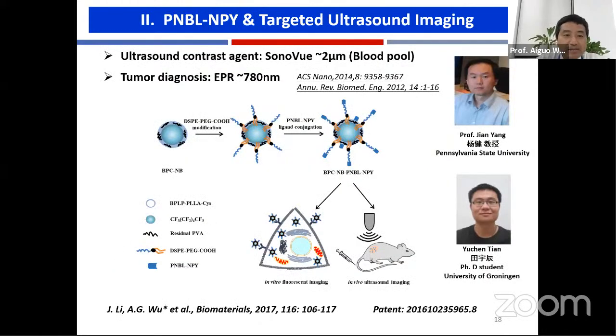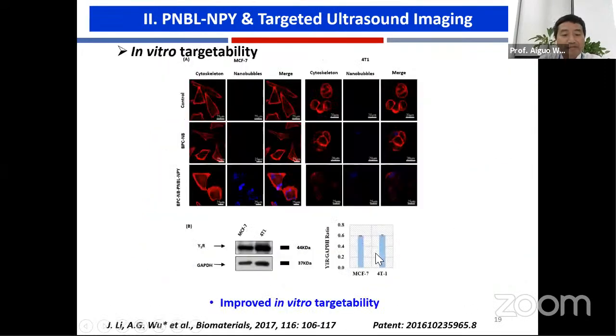And the second case I want to show you is where we attach nanobubbles to enhance ultrasound imaging. And here we prepared the nanobubbles. The bubble is about 200 nanometers. And then we attached DSPE-PEG on the surface. And these materials are from Professor Jian Yang from Pennsylvania State University. And then we formed the nanobubbles and injected them into the tumor area to get the ultrasound enhancement there. And we found it can improve the in vitro targetability of the nanobubbles.